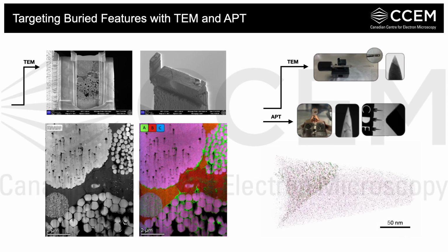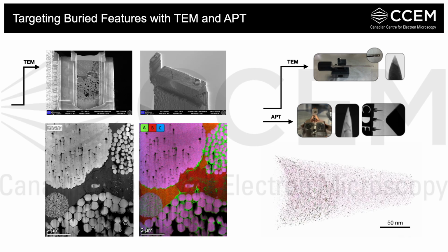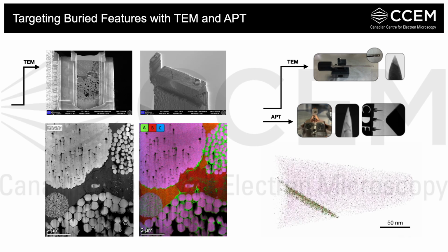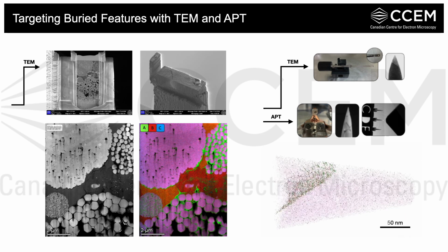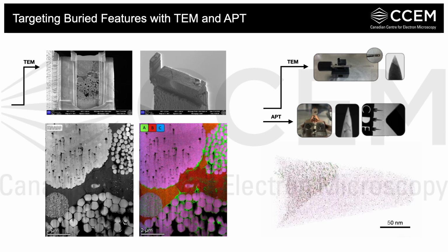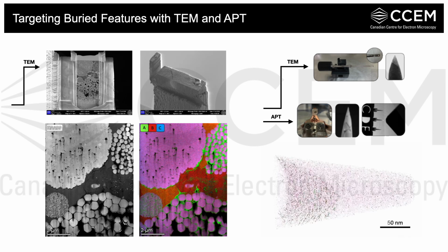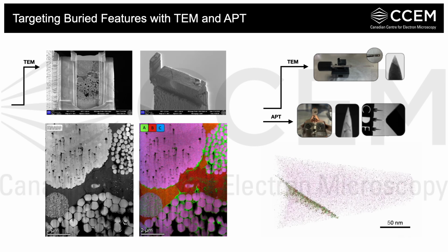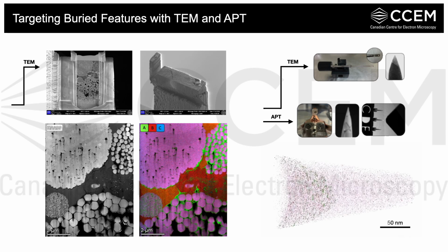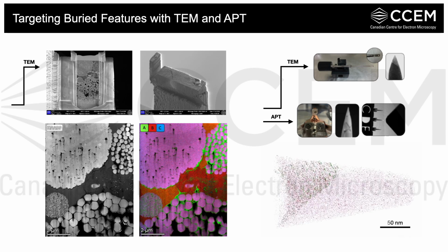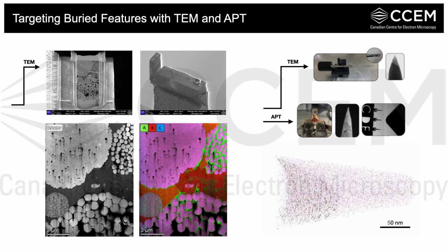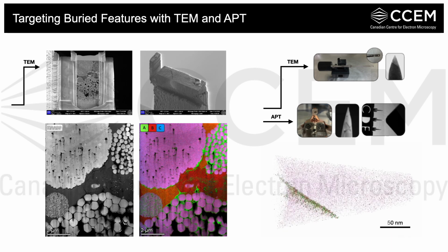And here are those results. So for TEM, we were able to prepare a standard surface lift out from the block, and now we can see even the smallest of our individual framboid grains with more detail, and we can see the variations in chemistry within these grains and the material around them. And since we collected EDS of the surface in the SEM, we can compare those results with our STEM images here.